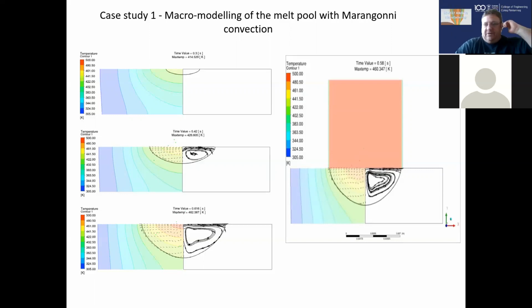Yeah, good. That's right. And this is the example that I gave you a couple of weeks ago, where potentially small impurities in the composition of 316 steel, particularly the sulfur, are known to go through a very small threshold in parts per million, where if it goes above a certain amount, the Marangoni convection will go differently. And this is actually a phenomenon.